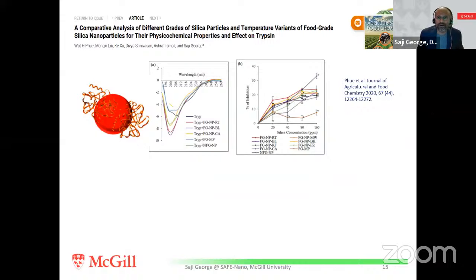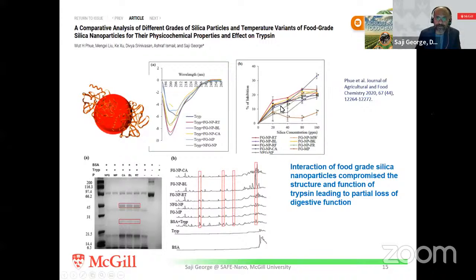So here is an example of nanoparticles like titanium dioxide or silica interacting with the digestive enzymes. For example, here it is trypsin, and we can see the structural change in trypsin using CD, that is circular dichroism. So we can see how much alteration in the secondary structure is happening because of that interaction. And we can also assess the inhibition of enzyme activity, and we find that there is a partial loss of trypsin activity because of its interaction with nanoparticles, but not with microparticles, and that will lead to partial digestion of the substrate.